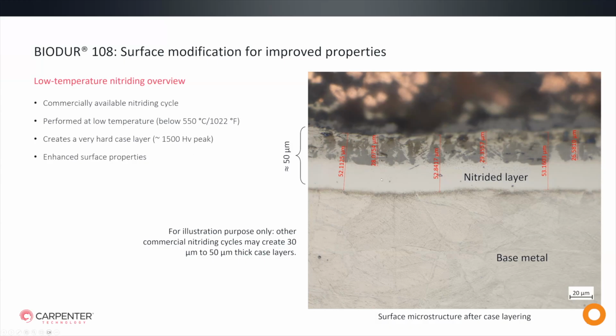But what this shows is that we have even further wear resistance and improved fatigue life without compromising the corrosion resistance or the bulk properties within the BioDur 108, as we explain and identify within the patent. And this is really beyond what I showed in the previous slides where we talk about wear resistance versus cobalt-chrome-molybdenum. This would be even further, and those tests for wear have not been performed. Again, nitriding is a diffusion process that's enhancing the hardness of the material itself, and it allows for the base properties of the metal to continue to perform without the fear of a coating coming off, for example.